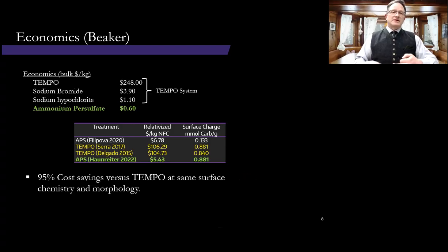And you can see that to make 1 kilo of nanofibrillated cellulose using the TEMPO method costs nearly in the range of $104 to $107 per kilo, or about 20 times what ammonium persulfate is. In my process, I can produce the same level of surface charge and morphology for about $5.50. So it's about a 95% cost savings versus TEMPO.